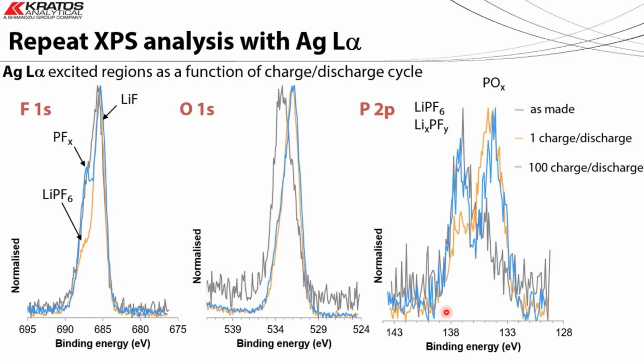So colleagues then repeated the analysis with the silver excitation source, and much the same as Stuart pointed out, we can see that our signal to noise is not so good with the silver excitation source. We can obviously count for longer to improve that, but with such mobile light elements that we're analyzing, as well as the fluoride materials, I think acquisition time was kept to a minimum. The chemical shifts that were observed were mirrored, with very similar changes in the chemical states as a function of charge and discharge.